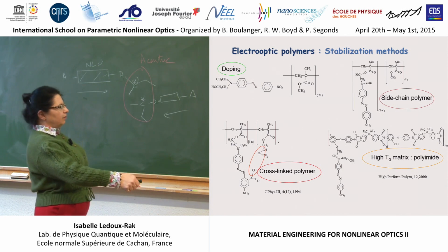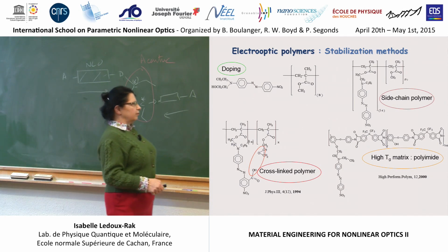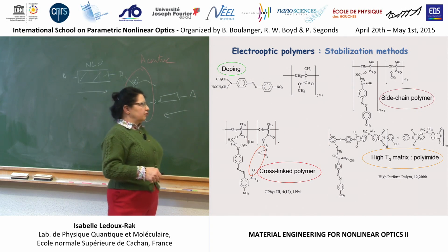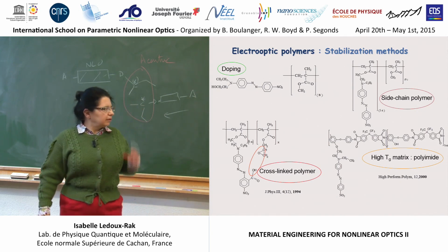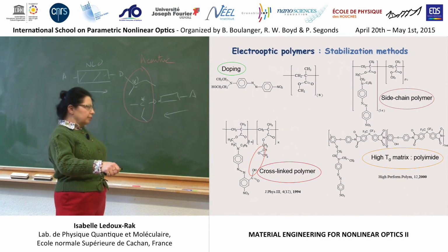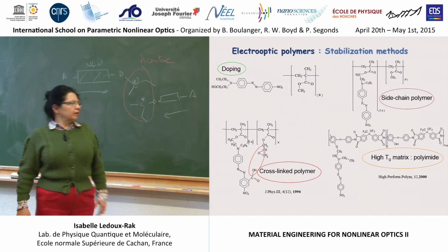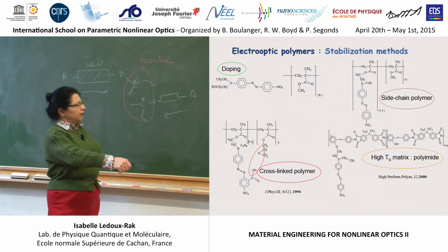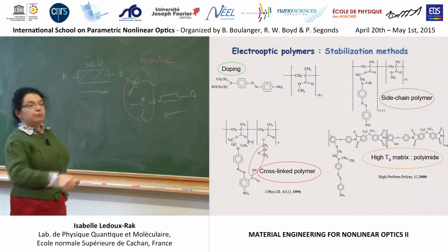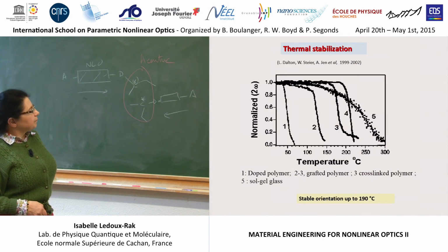But polyimides are much more rigid. They have a high glass transition temperature, and big expectations were put on this structure, but unfortunately, this is relatively too rigid, and molecules can be oriented, but there is a strange relaxation process after that, and polyimides could not be kept in this scheme.